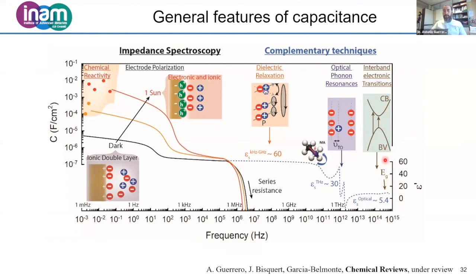And with the band gap of the perovskite, we can probe optical phonon resonances, for example, using terahertz spectroscopy. And at lower frequencies, we have the dielectric relaxation processes, for example, reorientation of the methyl ammonium dipoles as they follow the alternating electrical field. So by using these techniques, a static permittivity of 60 has been calculated in the range of kilohertz to gigahertz.